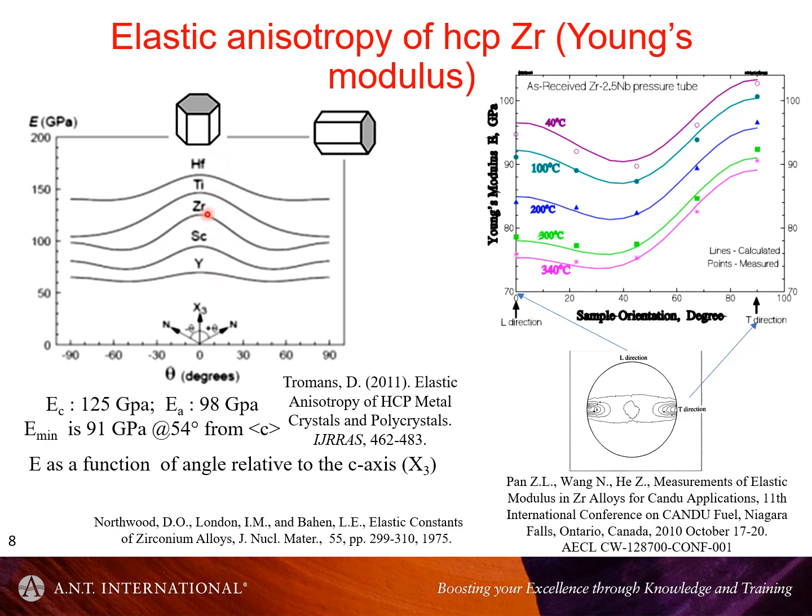And what this shows is that perpendicular to the C-axis up here, the material is strong, elastically strong. The displacement you would get by the imposition of a tensile stress on the C-axis is relatively small in that case, because it's stronger in that direction. It doesn't deform as easily. Whereas in the prism direction, it's much softer.